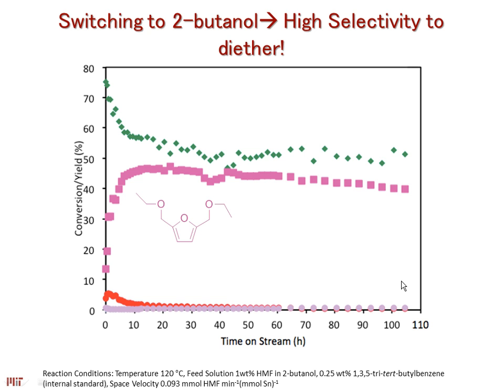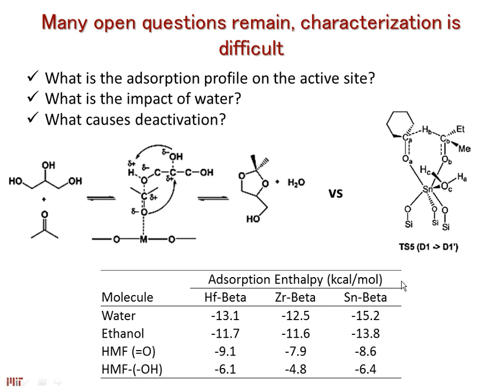We still create water. We create a little bit less water with the butanol system because we are not creating the acetals, but water has a huge impact on the catalyst itself. It is not leaching. It doesn't make the catalyst leach, but it actually changes the local environment around the tin site. We see these double hydrolyzed sites, and this is still work in progress, but we're starting to see very interesting effects of water in these long-term studies on the active site as well, even though we are not leaching the metal out of the framework.